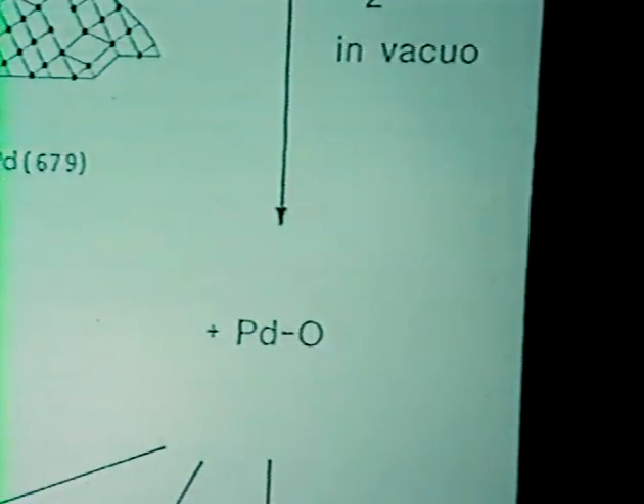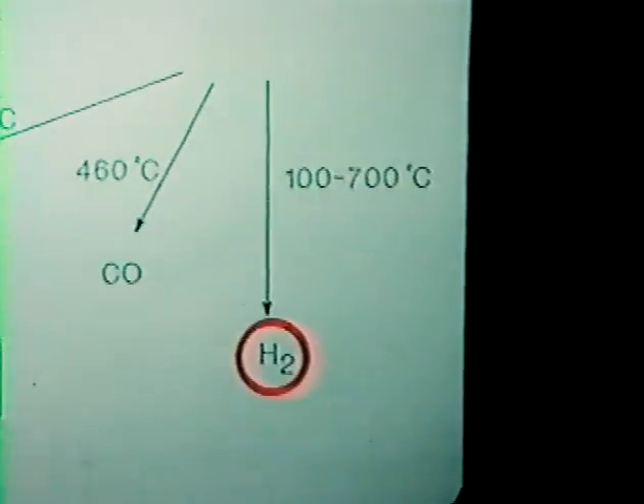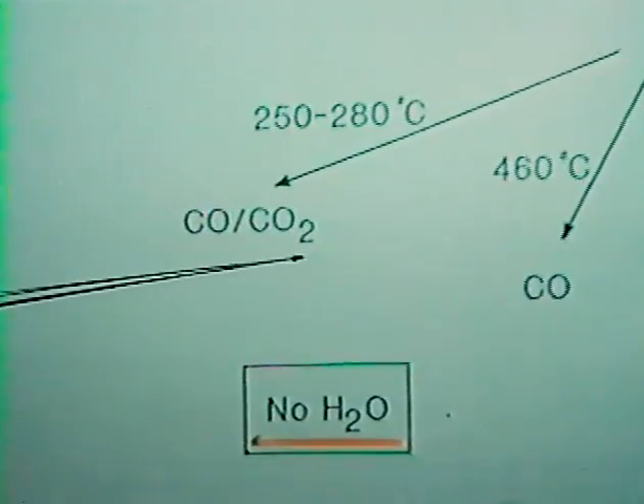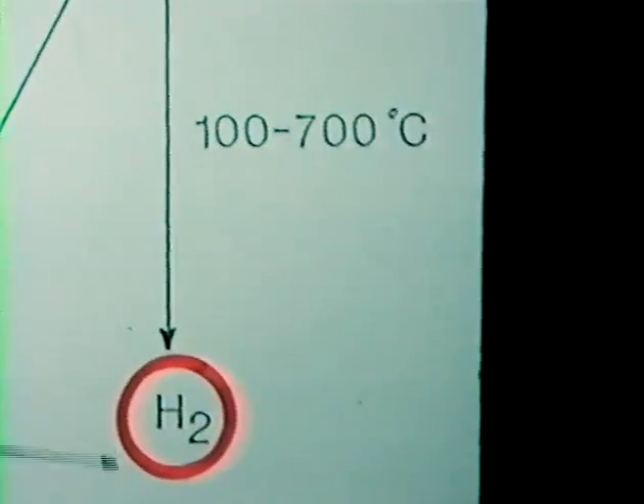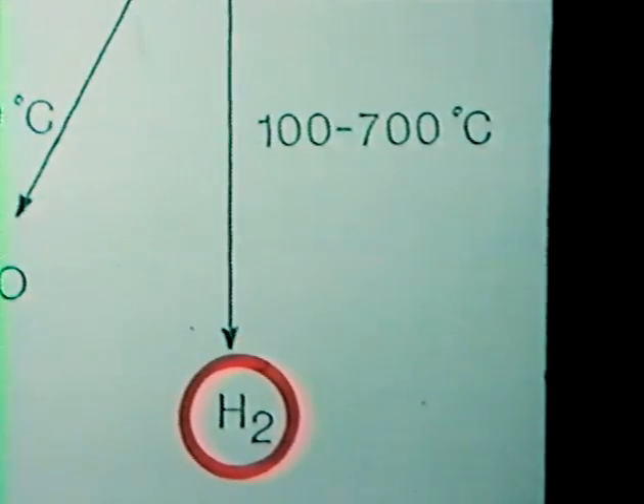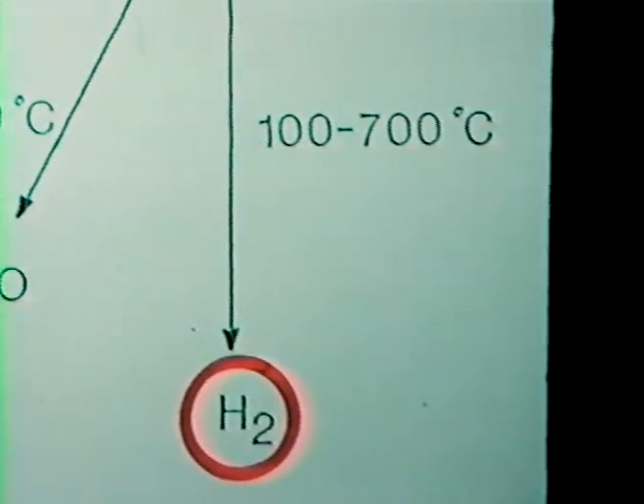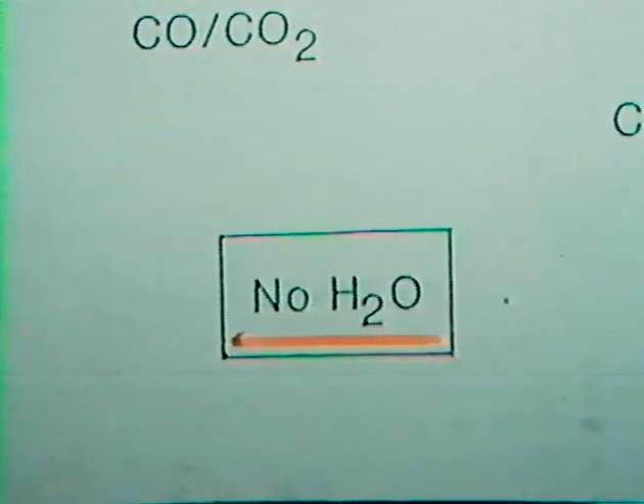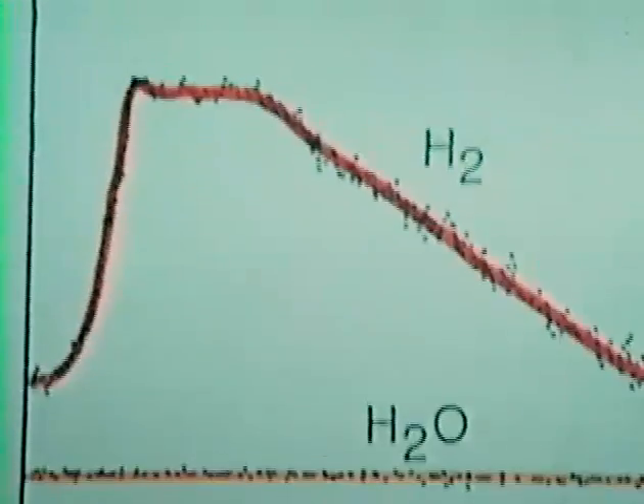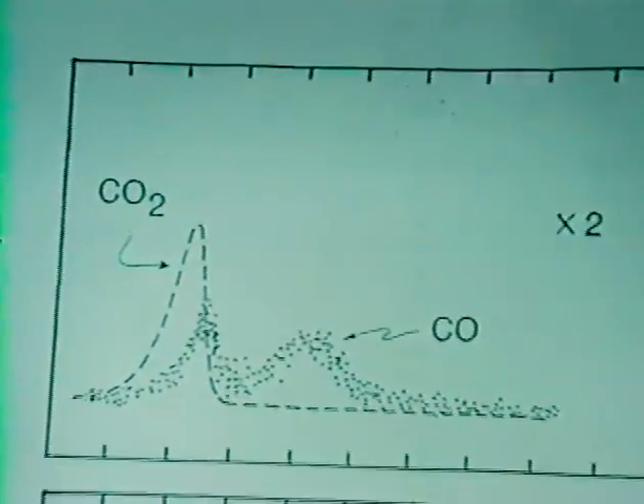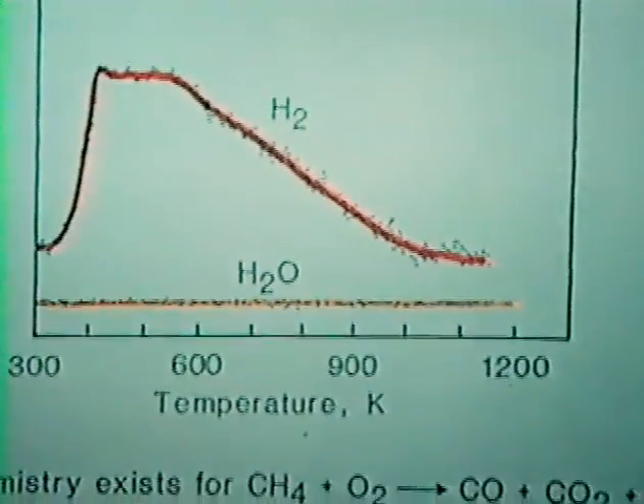Then one brings in oxygen onto the palladium at room temperature after vacuum. One evacuates and still nothing happens. Then one starts cooking the crystal to higher temperatures. And at relatively moderate conditions, carbon monoxide and carbon dioxide comes off. There is another state of carbon monoxide which comes off at higher temperatures, and there's a very broad peak of the product that really wouldn't be expected under oxidation conditions on palladium, and that is hydrogen. And I will show you on a slide that there is absolutely no water in this oxidation catalysis under these conditions as a product. This palladium crystal makes by oxidation of methane, stepwise produced, carbon dioxide, carbon monoxide, and hydrogen, and no water whatsoever. This is a very interesting result.